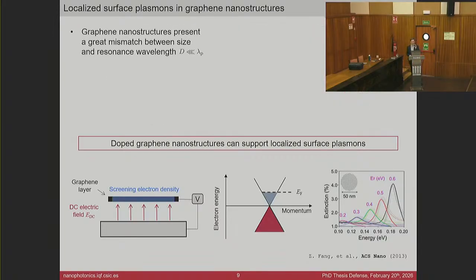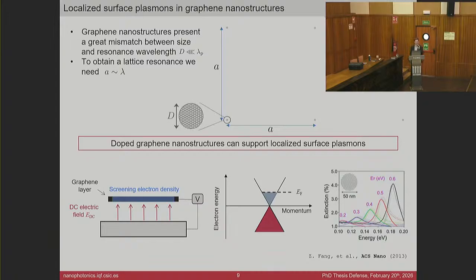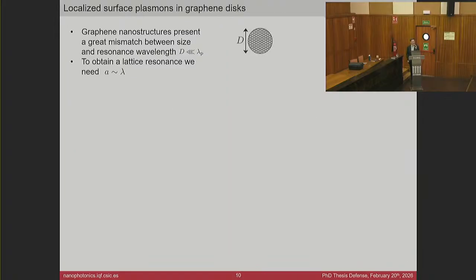Because in order to achieve a lattice resonance, as I was indicating before, we need a wavelength that matches the periodicity of the array. So if we try to achieve a lattice resonance with this size of nanodisk, we're going to obtain this kind of array, in which the graphene nanostructures occupy a really small portion of the array. We have a really small filling fraction. And indeed, to observe that this is indeed a graphene nanodisk, I have to zoom in, right? So let's see how we can solve this problem.